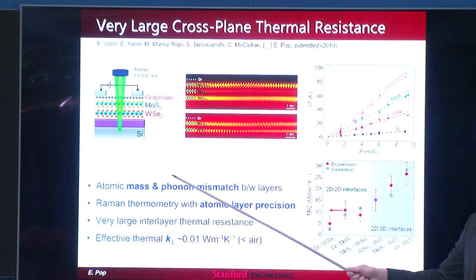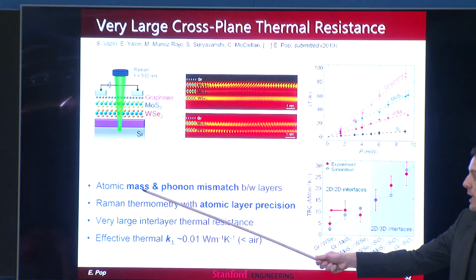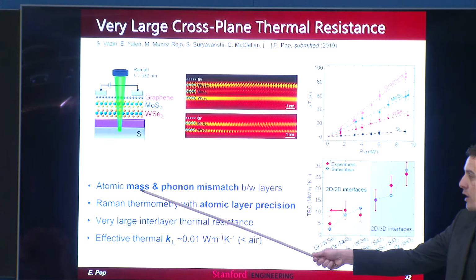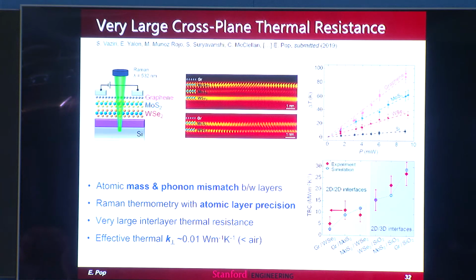What we're doing, deliberately, obviously, is mixing and matching layers that have very, very different atomic mass and phonon density of states mismatch. And if you do that on top of the weak van der Waals bonds between the materials, you actually get these very, very large interlayer thermal resistances. So the cross-plane thermal conductivity of these artificially stacked materials is way, way worse than Mother Nature. In fact, it's worse than air. For a solid material, this is pretty bizarre. It's really an excellent phonon blocker. That's basically what it is.